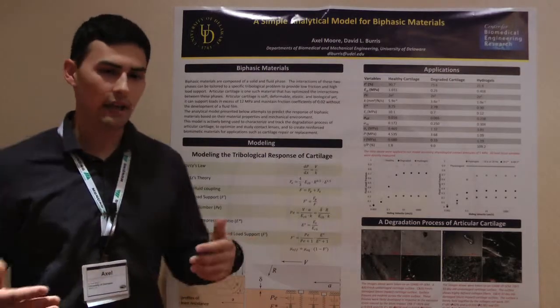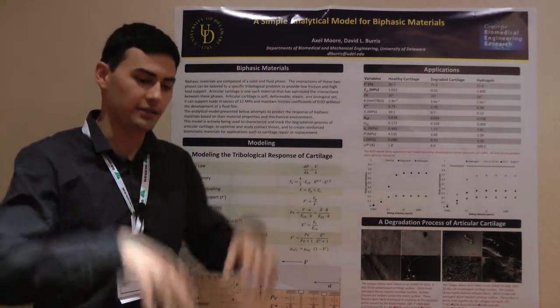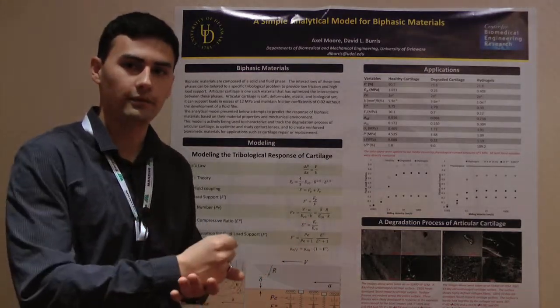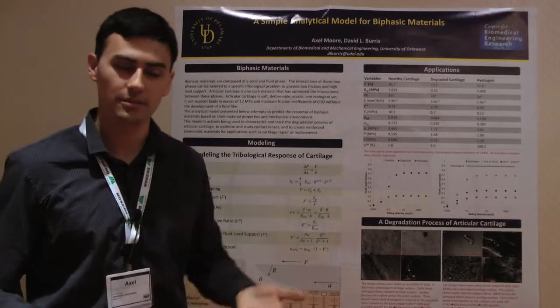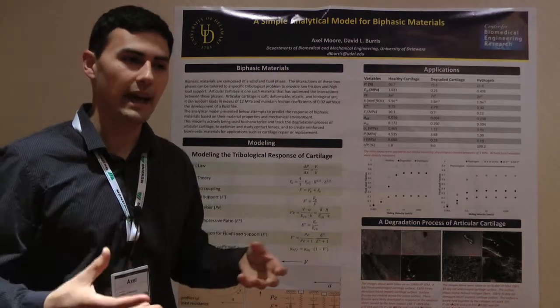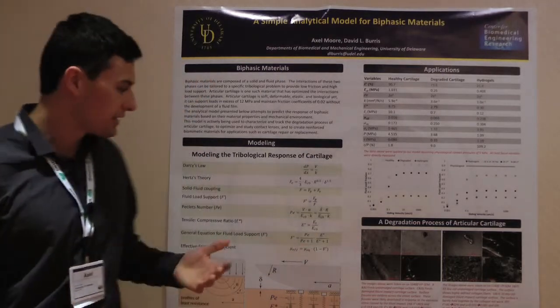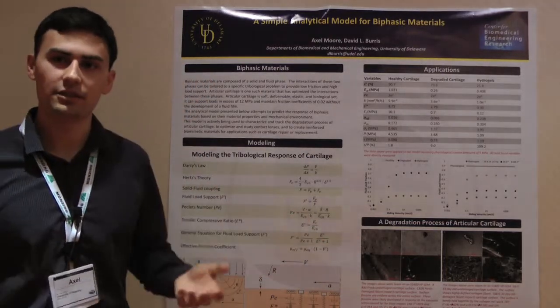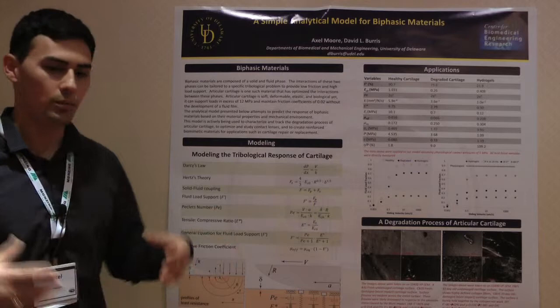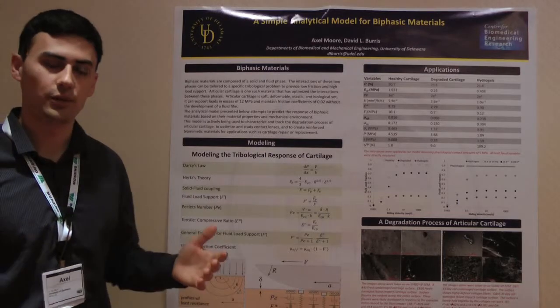The basic idea is: if you imagine running over water, if you run fast enough, you won't sink into the water. If you run slow enough, you're going to sink and hit the bottom. The idea is if you move the cartilage contacts quickly enough in your joints, you're not going to defeat this fluid load support property — you won't let the fluid move out from under you. We test these conditions at physiologically relevant speeds, and by moving quickly enough, we maintain this interstitial fluid pressurization mechanism.